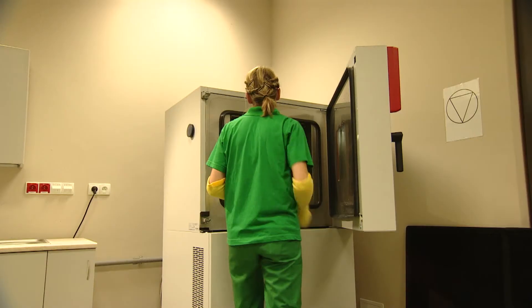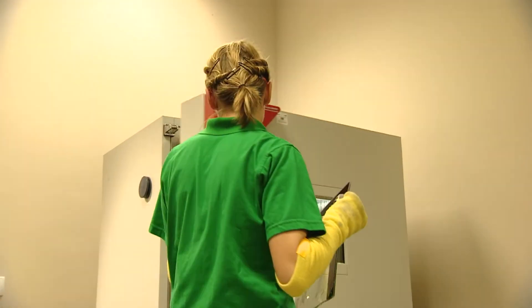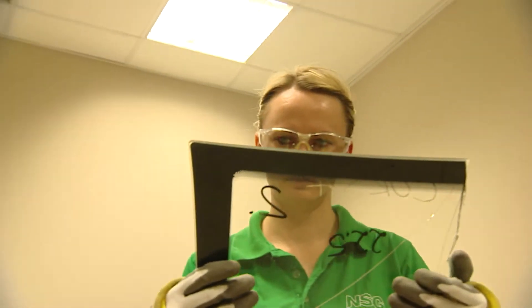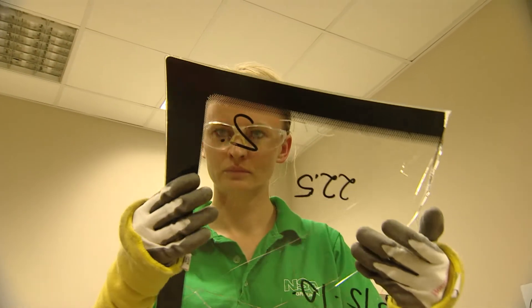The aging of laminated glass under severe weather is tested continuously by testing that accelerates the aging process. The glass is held at high humidity and high temperature for 14 days. Our sample has passed the test, but we keep on checking.